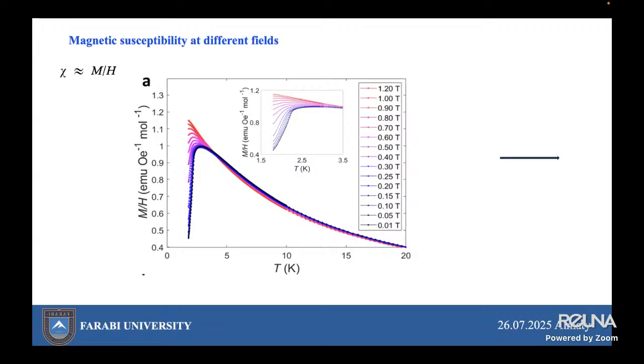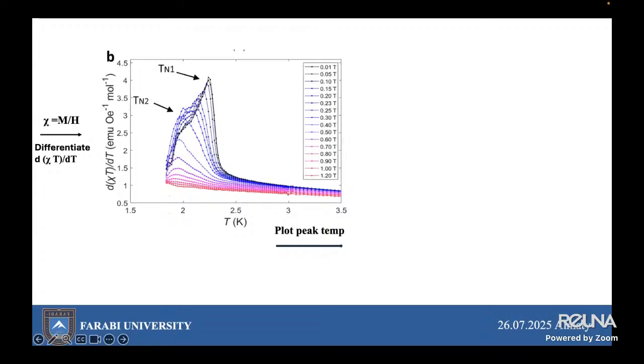And after that, we took the derivative of the product of the magnetic susceptibility with respect to temperature. This we differentiated as a function of temperature for the selected fields shown previously. You see that at 0.01 Tesla, a sharp lambda-type feature is observed at 2.25 Kelvin, which corresponds to the Néel temperature. This indicates the onset of three-dimensional antiferromagnetic ordering.